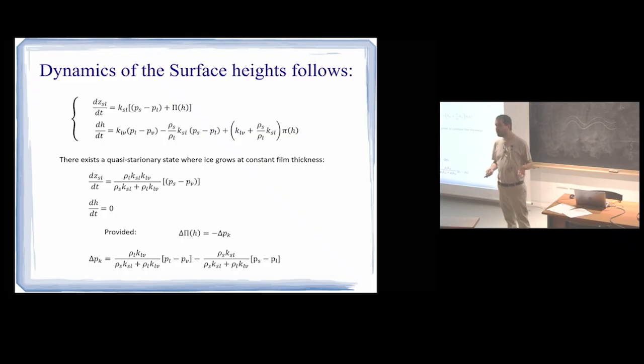But now I am doing out-of-equilibrium phenomena, and I have replaced delta P by delta P sub K because this is a kinetic pressure difference. Look at it. It's a weighted average of the thermodynamic fields that drive the system out of equilibrium times the kinetic coefficients in the equations. So it's really a beautiful equation because it's a very simple way to extend the thermodynamic theory to describe the dynamics.